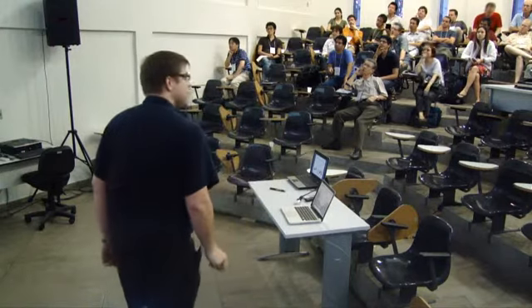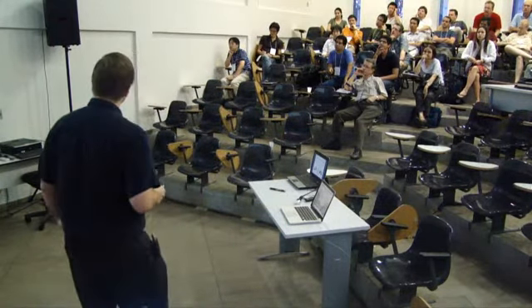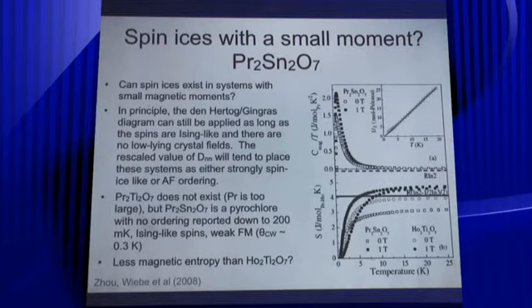Okay, what about small moments? So I mentioned that large moments is one of these strong dipole interactions for spin ices. We were looking at praseodymium stannate. I mentioned that the titanate doesn't exist. It's because of a size issue. The praseodymium and titanium size doesn't give you the cubic pyrochlore lattice if you compare the A/B ratio. However, you can make the stannate compound, and in principle, you can use the phase diagram to look at compounds that have small moments, but because your D is so small compared to things like holmium and dysprosium that have 10 Bohr magnetons compared to a few Bohr magnetons, you're going to be either far to the right or far to the left of that phase diagram.